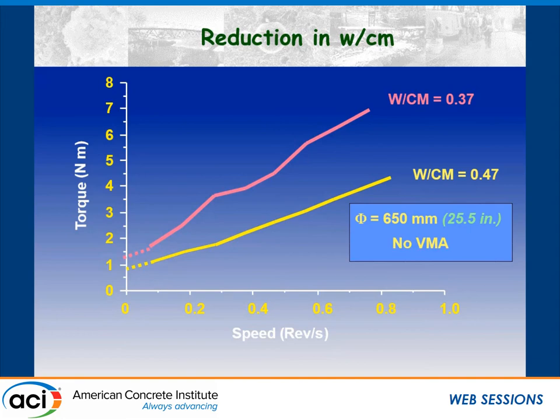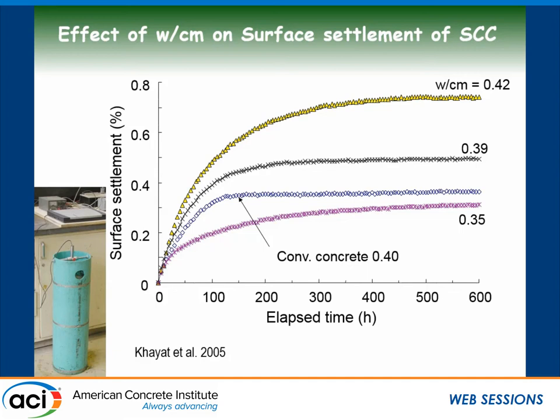So if you were to look at the surface settlement of concretes like this, these are all SCCs with exactly the same slump flow, same yield stress: 0.42 water cement ratio, 0.39, 0.35 in pink, and then as a reference one is 0.4 with internal consolidation. For the three SCCs, 0.42, 0.39, 0.35, you could see that the settlement is decreasing. A number to keep in mind, which I'll mention later on, is 0.5% settlement. The settlement here is expressed as a percentage of the concrete height. So if you're filling the concrete 600 mm, this will be three millimeters of surface settlement.